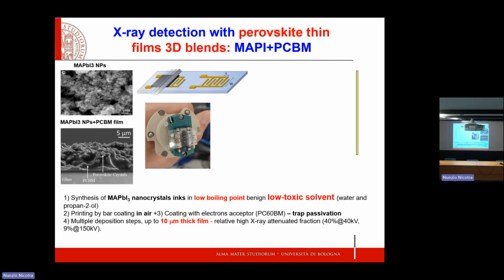And here is what a very simple 2-terminal device looks like. Here you see like 4 or 5 pixels. What is interesting with perovskite is that they have a higher atomic number, and you can deposit them up to 10 micrometers thick. So with perovskite, we exploit not the human tissue equivalence, but the fact that we can still keep a flexible plastic device with a much higher absorption cross-section for radiation. So we can stop higher energy photons.